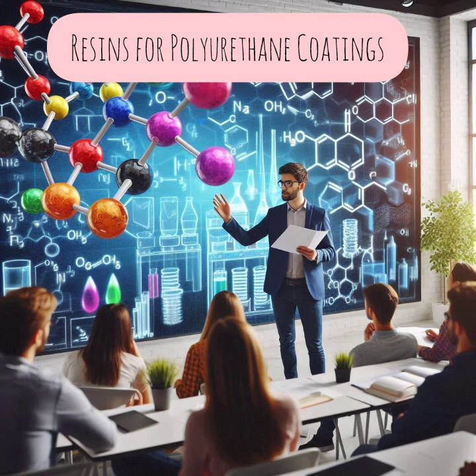They are excellent as a UV-resistant topcoat to protect the epoxies from direct sunlight when cured with an aliphatic isocyanate, HMDI. That is why most multicoat protective coatings contain an epoxy primer, an epoxy undercoat, and a PU topcoat of an acrylic polyol with an aliphatic isocyanate. The special outstanding qualities of these types of urethane coatings are abrasion resistance in addition to solvent, chemical and corrosion resistance. It can be reasonably claimed that no other coatings available have such abrasion and impact resistance properties. Hence, in addition to corrosion and UV resistance, they make excellent floor and deck coatings.